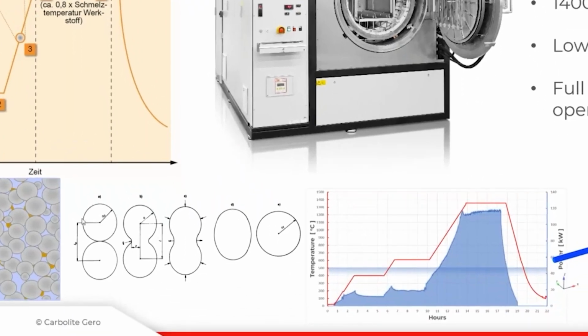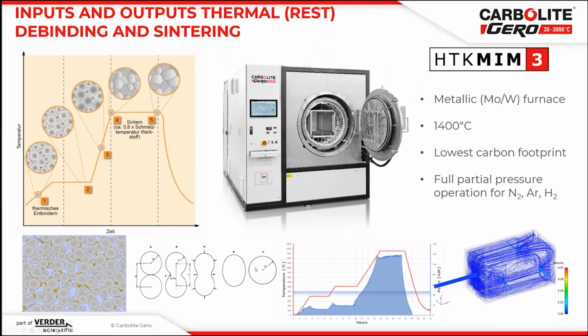You also see it here, you have two powder particles, and by material diffusion, you sinter the part to its final density. And this is the most important thing to understand in 3D printing about debinding and sintering, because this is true when I talk about a metallic part, but also for ceramics, it's exactly the same. But of course, the atmospheres are different.